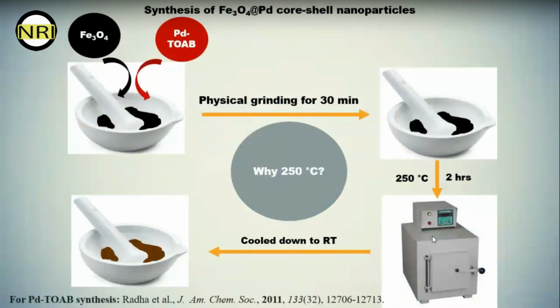So I have prepared these Fe3O4-Pd core-shell nanoparticles. I have synthesized this core-shell nanostructure by using a completely solid-state approach. But generally, people synthesize these core-shell nanoparticles by using a wet chemical synthesis process.